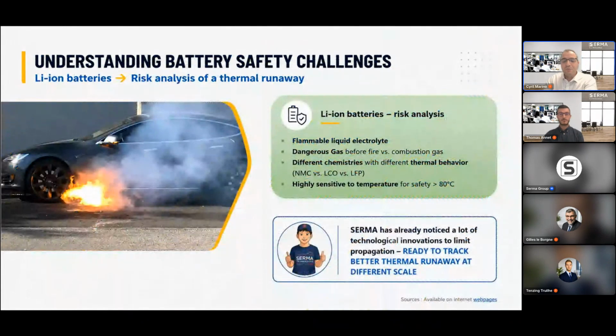So let's start. What can happen sometimes is that there is a failure. When we do a risk analysis of a lithium-ion battery, you see that when thermal runaway starts, the flame that you see is basically the electrolyte, a flammable liquid, which catches fire first. Then you have dangerous gases that evolve. They are emitted first when the cell is venting, and then of course there are also combustion gases. You also have different chemistries, LFP, NMC, LCO, for example, that have different thermal behavior. This is something you have to take into account in a risk analysis.